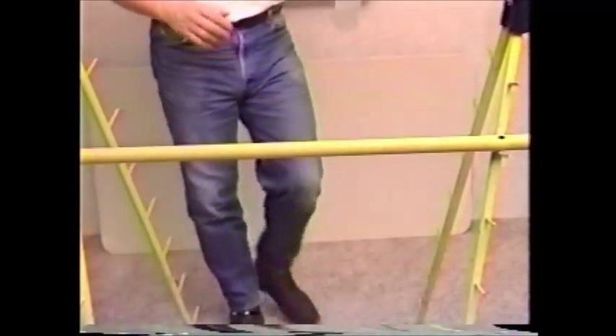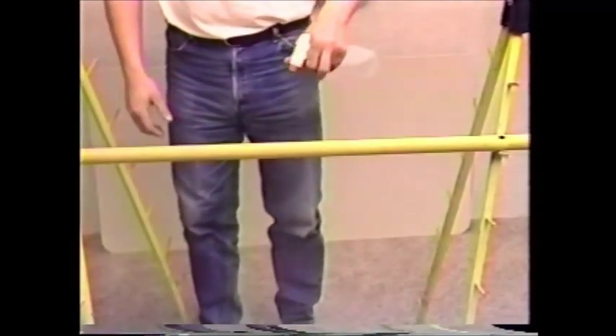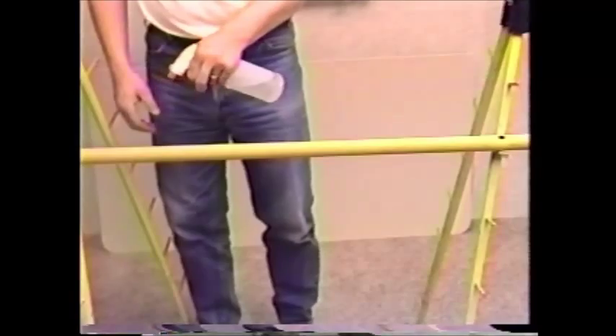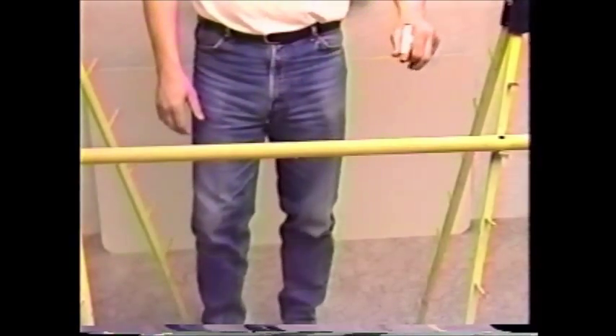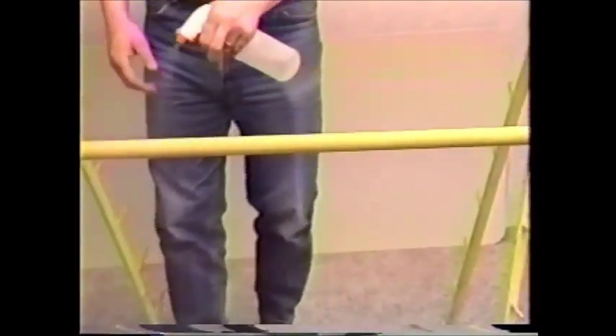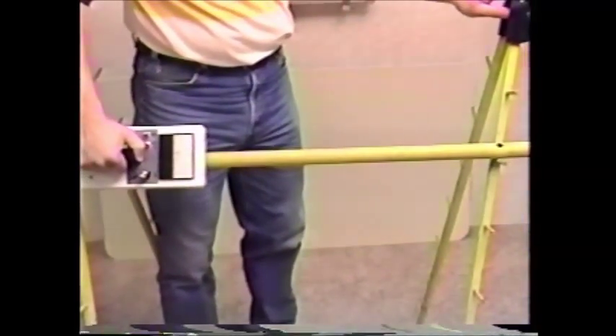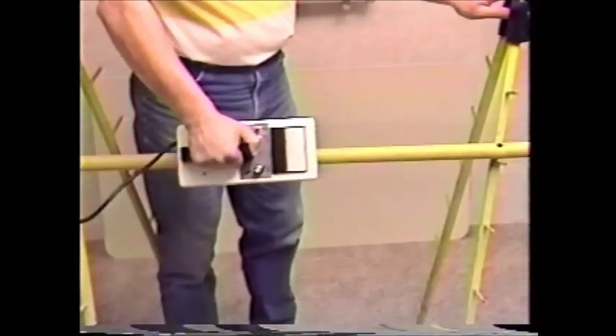We will repeat the test on a second tool. The surface shows more damage and contamination than the last. However, visual inspection is inadequate to determine how the tool will perform during the wet test. As the stick is wetted, you will note that the water doesn't bead as much as the first stick. Placing the tester on the tool, we will note that not only does the tool fail the test, but the meter is going off scale.